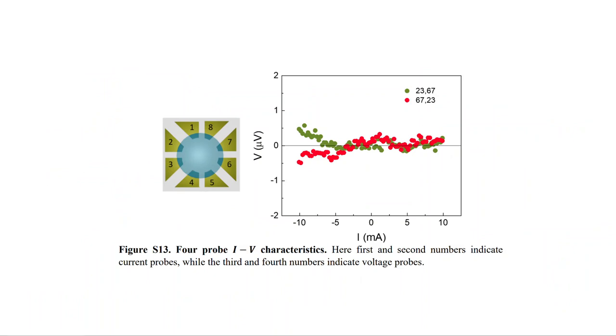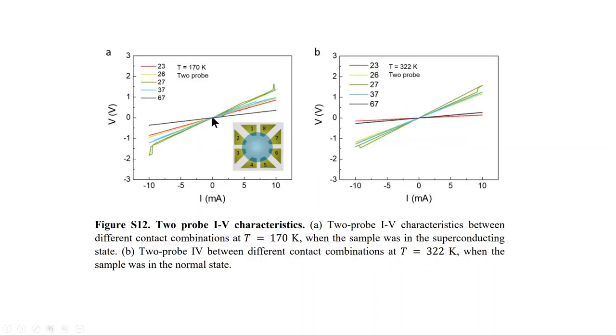In particular, in the very long supplementary document to the manuscript, they do show some 2-terminal IV curves, and these are the 2-terminal IV curves. So they show them at higher temperatures where they're purportedly in the normal state, and then they show them at 170 Kelvin where it's presumably in the superconducting state. They don't say which sample this is, or they don't show the IV curves in the 4-terminal IV curves in the superconducting state, but not doubting that part.